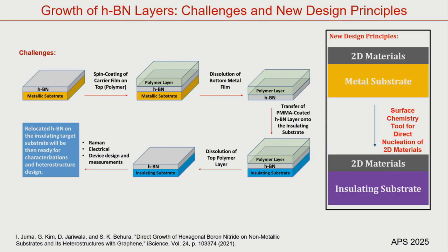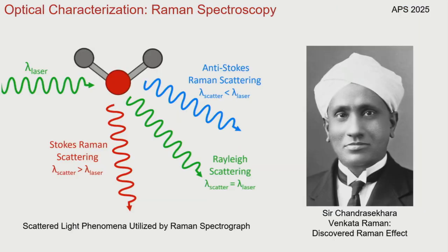Now, what a majority of labs do is that they directly deposit onto a catalytic substrate, like a copper foil. They spin coat a polymer known as PMMA onto the surface of that. They dissolve, they etch away that copper foil, usually using a strong acid, and then they put another substrate underneath, melt away that polymer, and then you can finally get something you can characterize and work with. Now, the problem with that is you can't necessarily control all the new defects you have induced in this process. So we're hoping for a better method, one that's a little bit more direct.